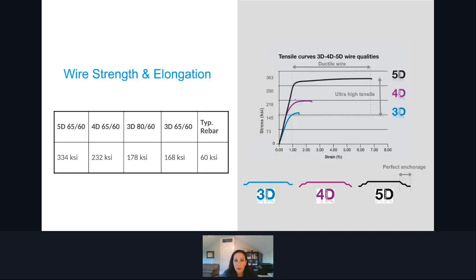Next is the wire strength, the actual tensile strength of the steel. So your typical reinforcing grade 60 rebar, maybe grade 75 or 80 welded wire mesh. Our 3D fibers tend to be around 3 times that at 170 to 180 KSI yield strength. Our 4D fibers are up at around 230 KSI, and our 5D fibers up at 330 KSI. So you can see that the distribution of these very high strength steel elements will provide a different amount of ductility and in a different way than your traditional grade 60 rebar.